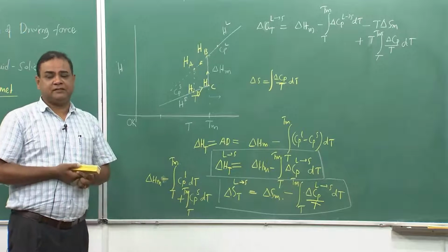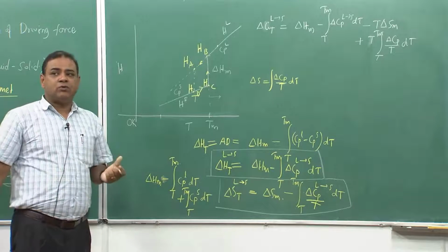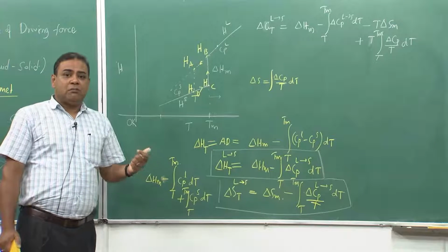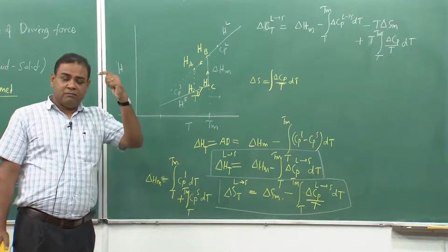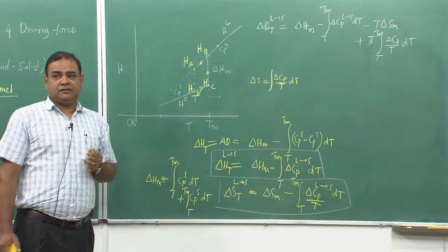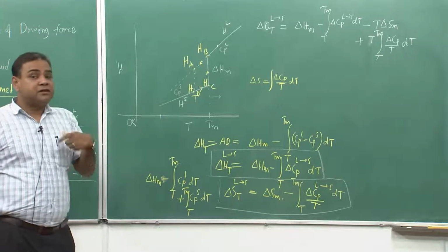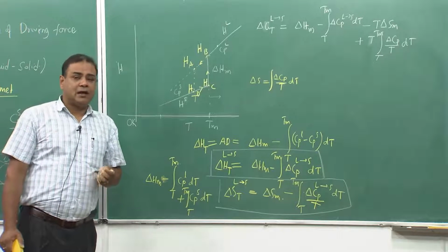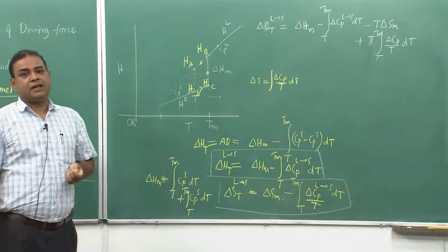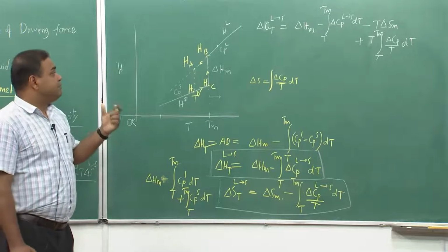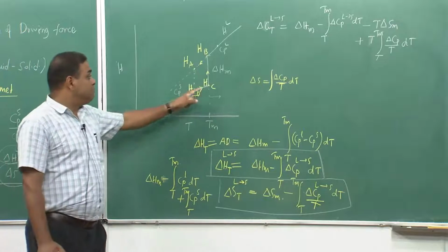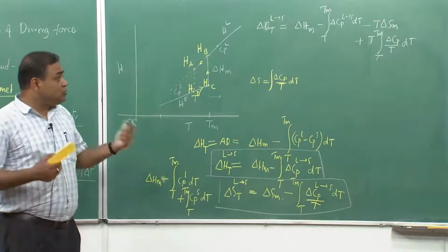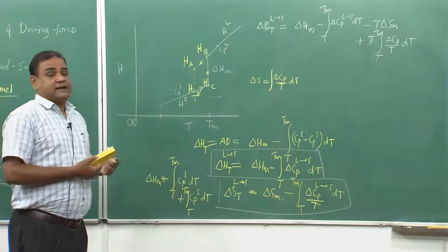But actually liquid water can be maintained liquid even below minus 40 degrees Celsius. That undercooling is possible if we allow homogeneous nucleation in liquid. At that time we can maintain liquid as liquid below melting point, and we can easily find out the Cp. People do calculate Cp of liquid like that.